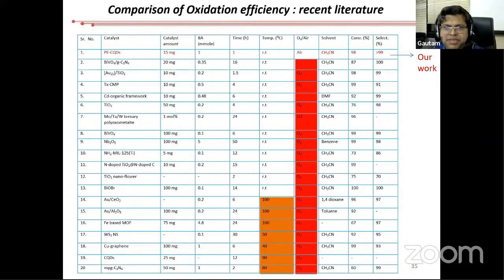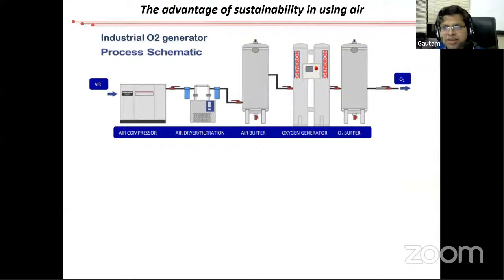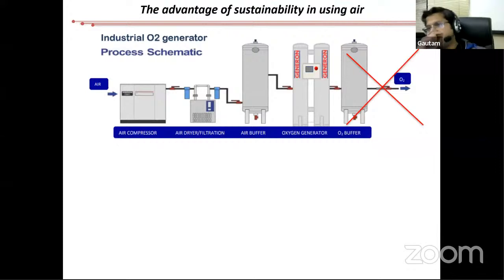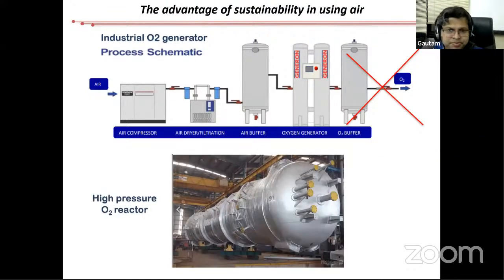So this is a chart, again, a very busy chart. You do not have to bother about it. The significance of this result is that we do not have to separate oxygen from air, which is an expensive process, if we can use carbon dots for industrial, large scale applications. This is a high pressure oxygen reactor, and if you use carbon dots, we do not have to use this kind of reactor. We can use simple reactors, and you can use air.